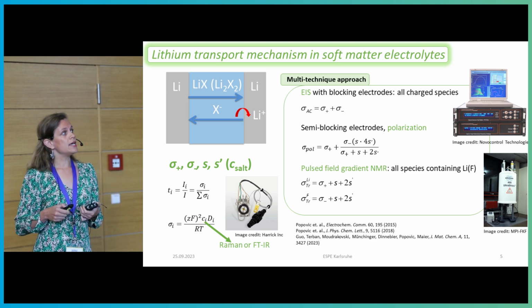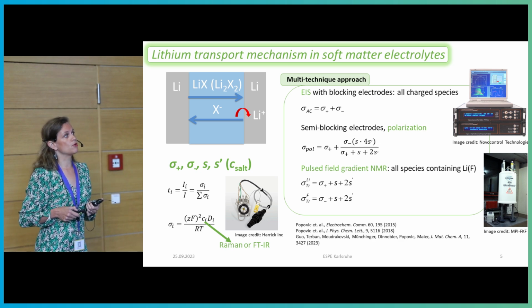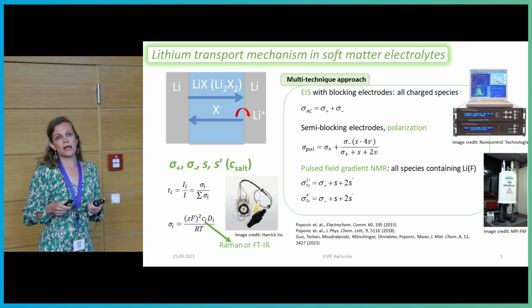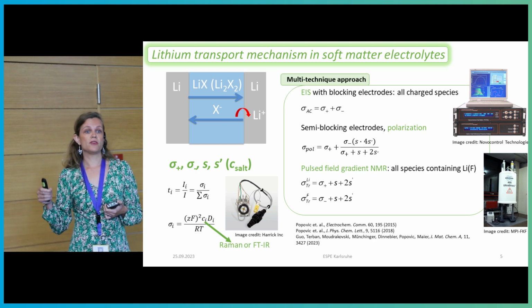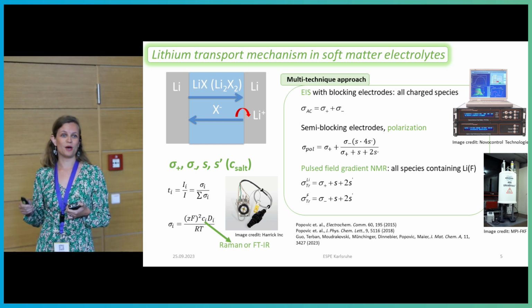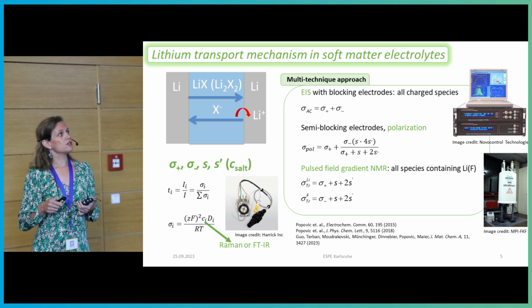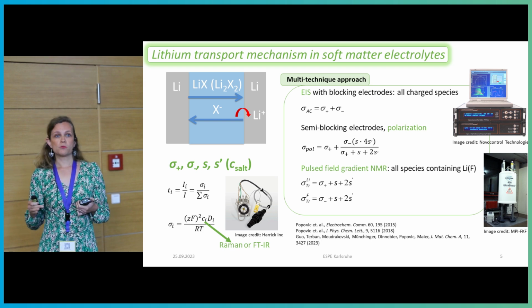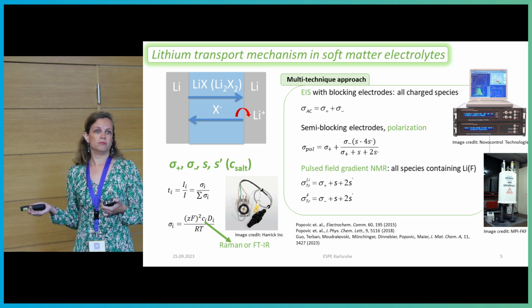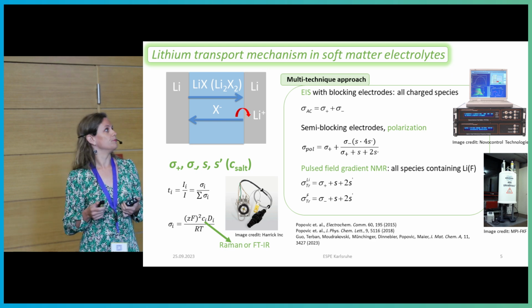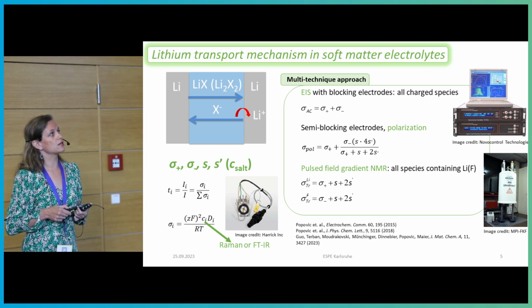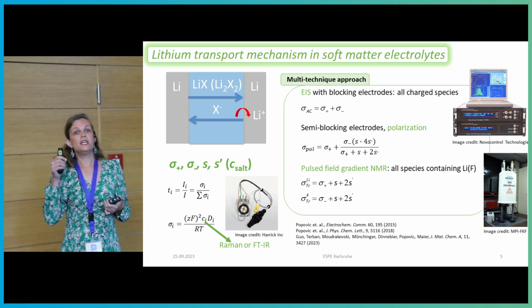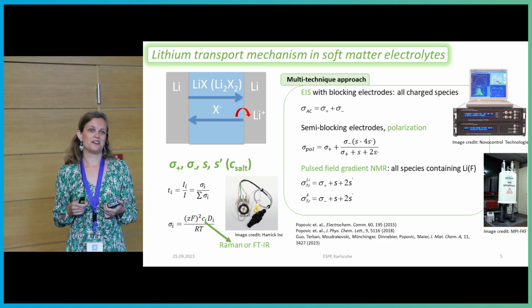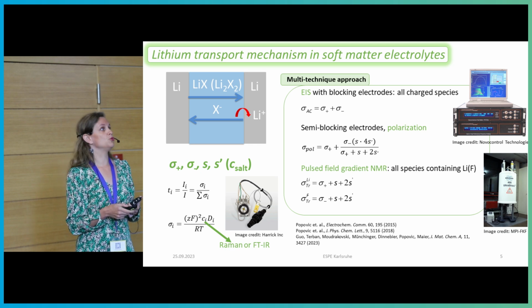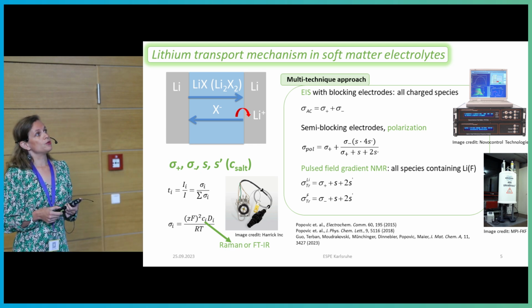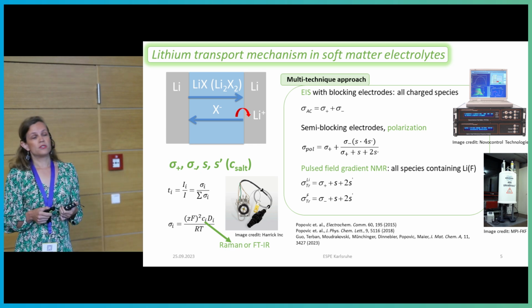And then if we are lucky enough and we can, from Raman or IR, extract the concentration of every specific species, and that is possible for some of the electrolytes, then we can have some equations with some unknowns, and we can simply calculate it from these equations. And then we can access the real transference numbers of each specific species, which is the beauty of this approach. So I would show you two examples of this approach.